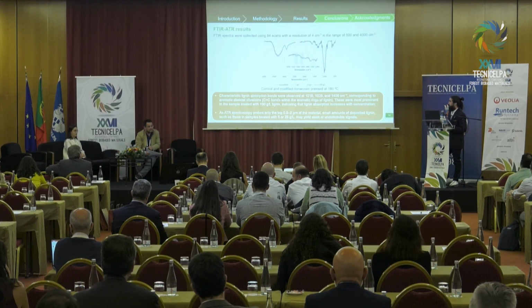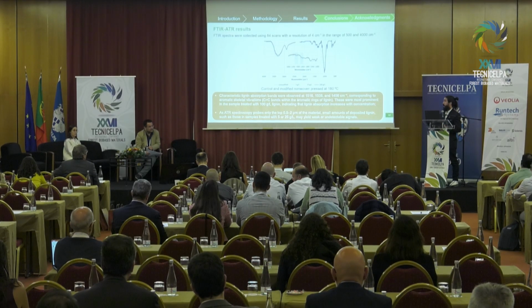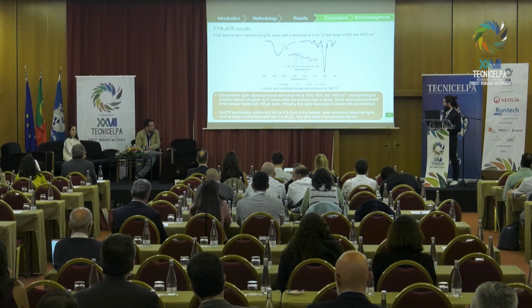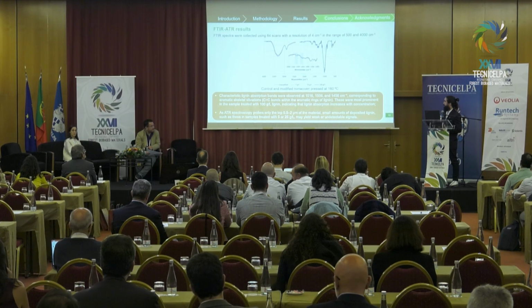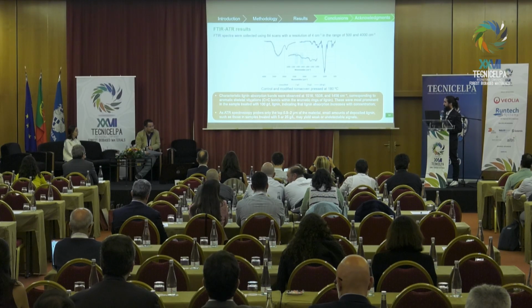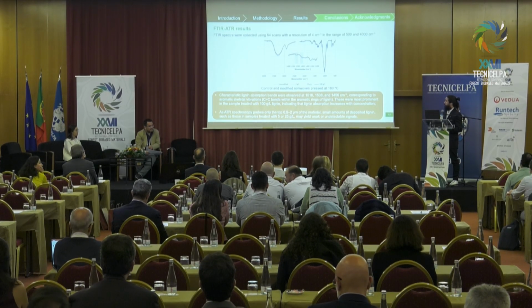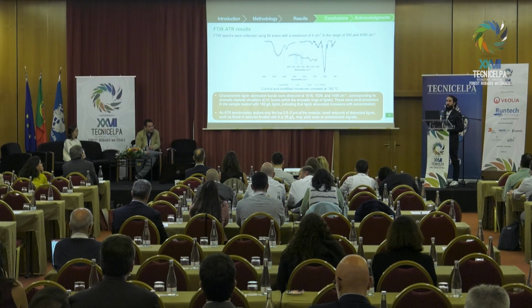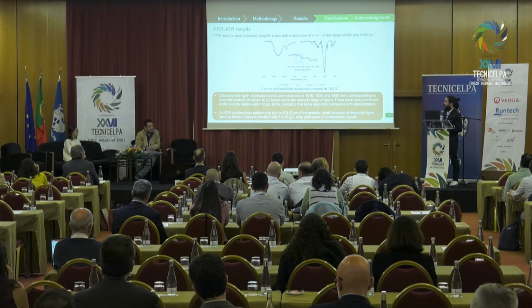Another test that we did was the ATR results to assess also if we indeed modify the nonwoven in the surface. As you can see here in these two identified bands, we identified some bands associated with lignin, aromatic skeletal vibration, double C bonds. However, they were more noticeable only in the highest concentration, but this can be due to a limitation of the equipment itself, because ATR only probes the top 0.5 to 2 microns of our material.